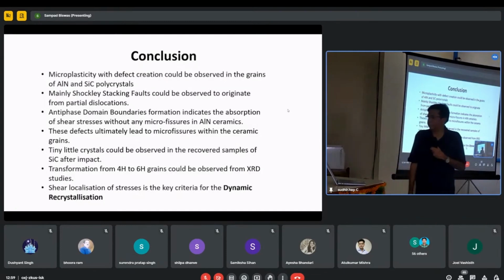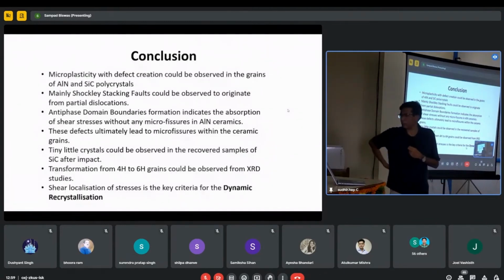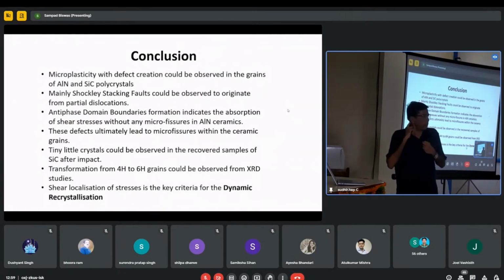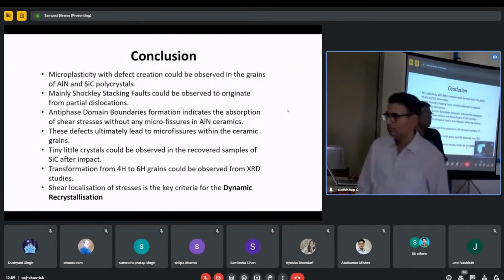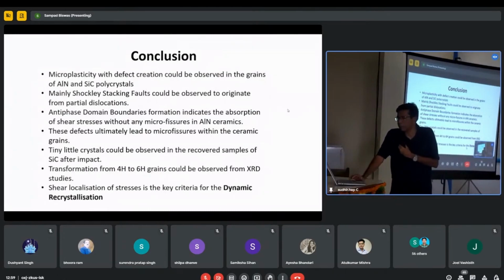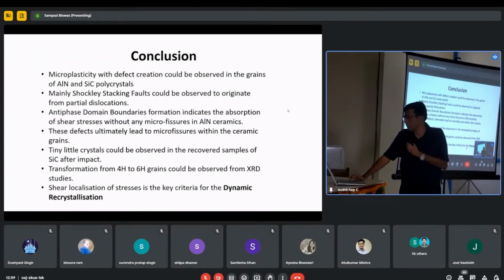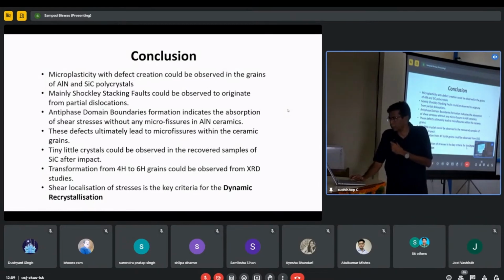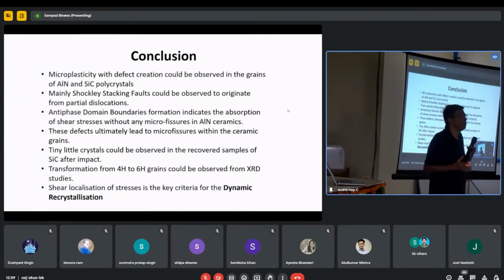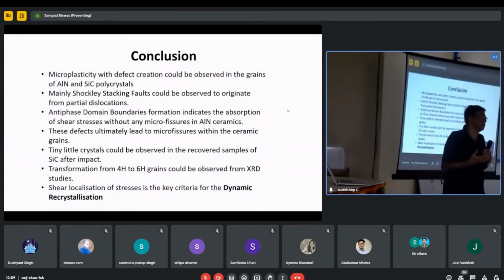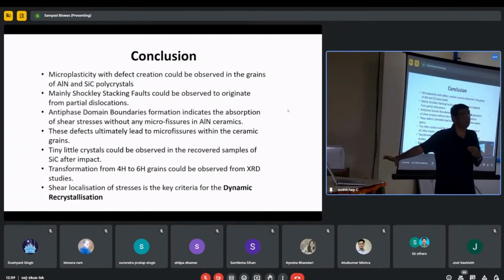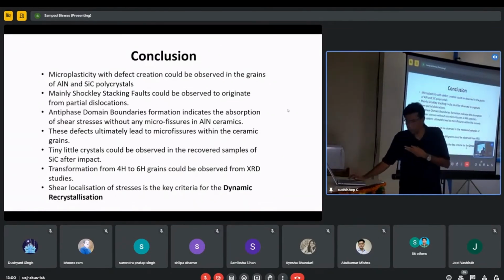So, the conclusion is that microplasticity with defect creation could be observed in the grains of both aluminum nitride and silicon carbide. Mainly Shockley stacking faults we could identify. We didn't find any Frank stacking faults or any other extrinsic faults. Antiphase domain boundaries could also be observed in aluminum nitride. These defects ultimately lead to micro fissures within the ceramic grains. Tiny little crystals could be observed in the recovered samples. So, dynamic recrystallization is the main process of microplasticity, and this has never been reported until now. So, we are going to communicate it very soon.